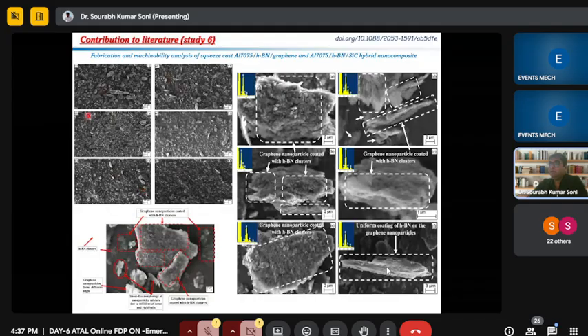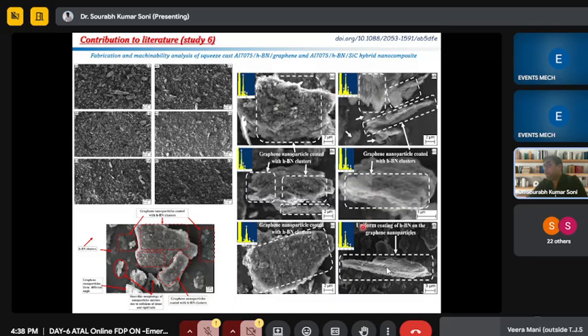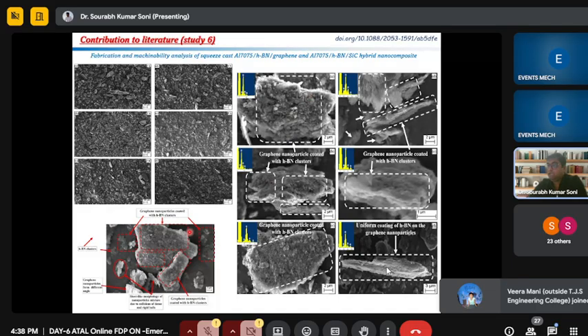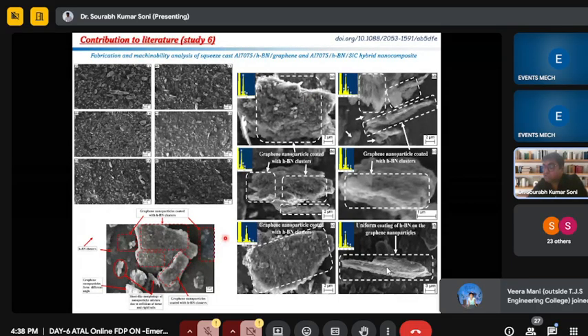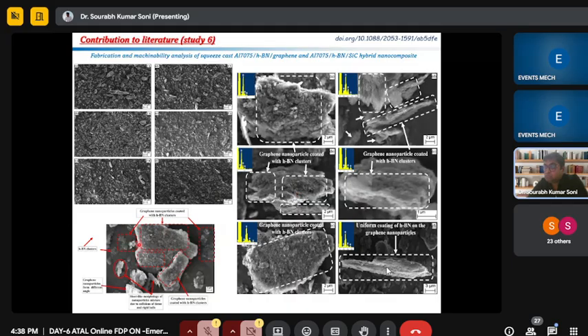From this same image, I have analyzed the ball milled reinforcement particle mixture. So what is going on after the ball milling? These are the high magnification images. Here we can see the HBN particles are uniformly coated over the graphene nanoparticles. So we can show this kind of morphology change after the dispersion technique. Here we can see that after the prolonged 6-hour ball milling, nanoparticles are highly stuck to the graphene particle, and the graphene particle is also flattened due to intensified ball milling.